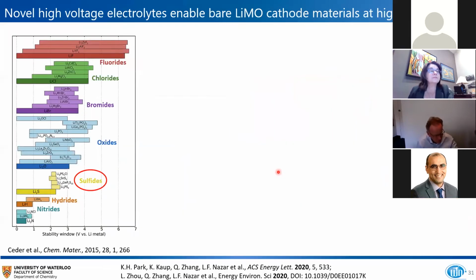So the argyrodite is a sulfide material, and that means, just like LGPS, it's not particularly stable at high potentials. In other words, it oxidizes around 2.7 volts, and all of the sulfides do this. And so that causes a problem for practical solid-state battery implementation.